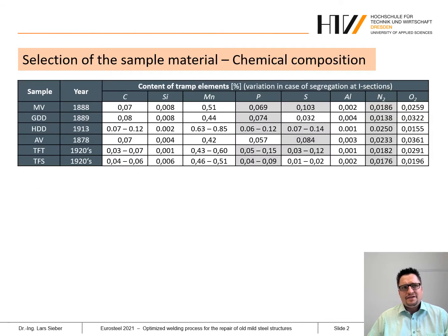We have intensively studied the butt welding of these old materials over 3 years. At the last conference, the last Eurosteel conference in Copenhagen, I was able to present the very first results of this research project. From almost 30 materials, we selected these 6 materials you can see here in this table for our investigations, from different years of erection, also different types of material and types of cross sections, steel plates as well as angle sections and so on. All these 6 materials are typical Thomas steels with a high content of phosphorus, which is very typical for Thomas steels, but also high contents of sulfur, and, typical for all the converter steels, a high content of nitrogen, which causes this aging effect.